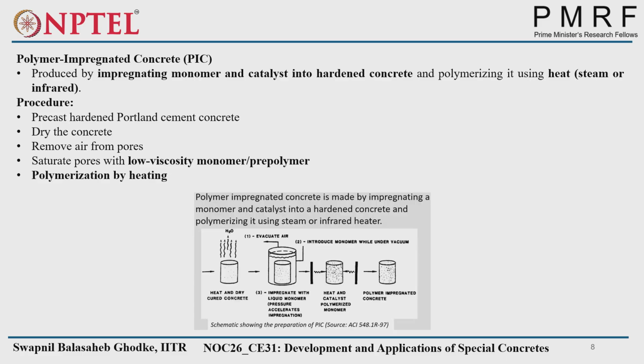We'll see it with the image also. Here you see we have a concrete cylinder. First of all, we heat and dry it to remove all the water from the pores. Then we keep it in the vacuum. In the vacuum, we impregnate monomer into the pores of that hardened concrete, along with the catalyst to initiate the polymerization reaction. Then we provide the heat, and at the end we get the polymer impregnated concrete.